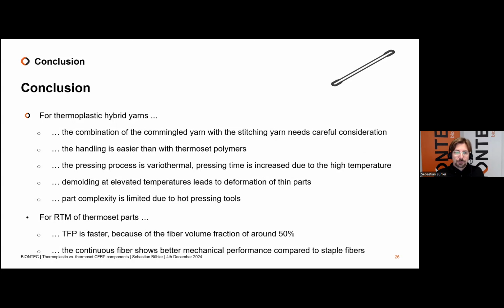For the RTM of the thermoset parts, tailored fiber placement, of course, is a little bit faster, because we only stitch the fibers and not the matrix, and the volume fraction is around 50%. And of course, the continuous fibers show a better mechanical performance compared to the staple fibers.